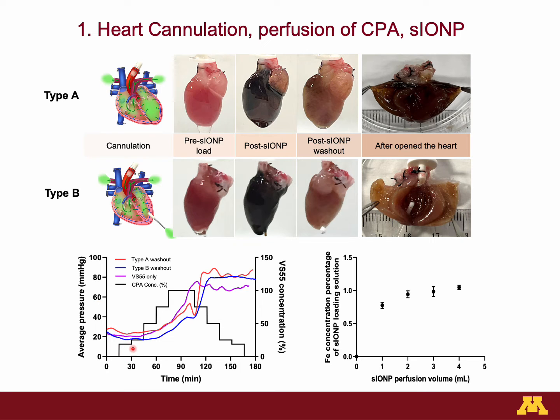In order to reduce osmotic shock, we load VS55 in a stepwise fashion with continuous pressure monitoring and a constant flow rate. When the perfusate reached 100% VS55, a new stream of VS55 loaded with iron oxide nanoparticles was perfused into the heart until the nanoparticle saturation reached the effluent. The heart turns uniformly black due to iron accumulation. Visually, the washout efficiency of the type B cannulation method was superior to that of type A cannulation.